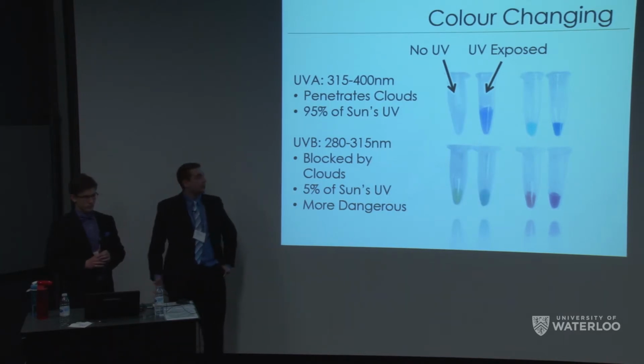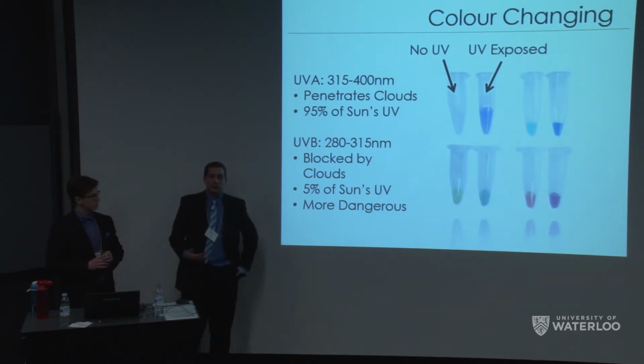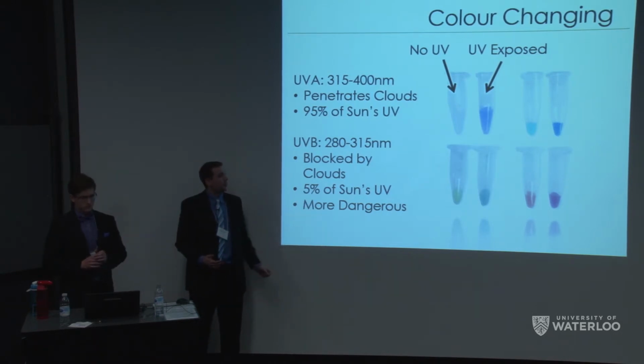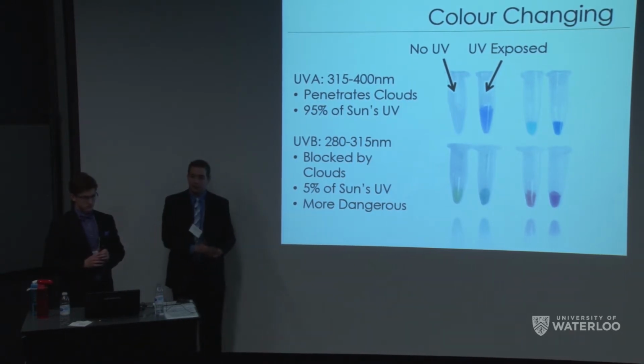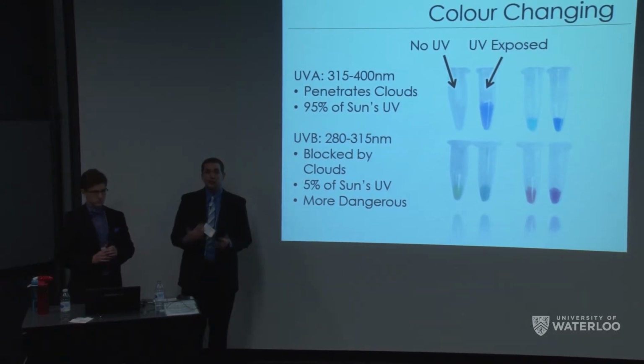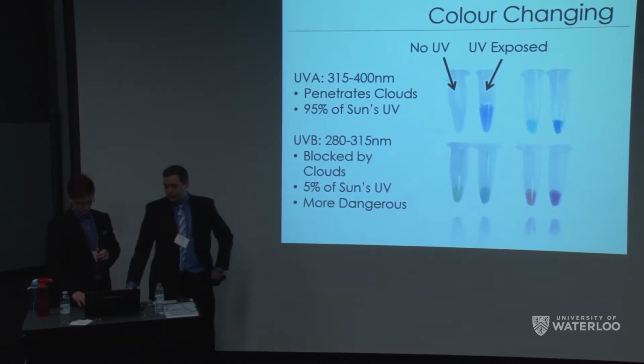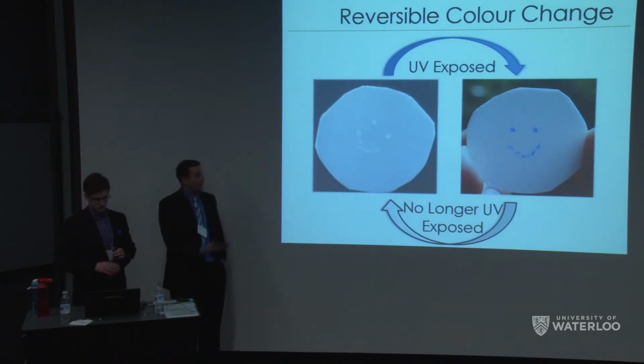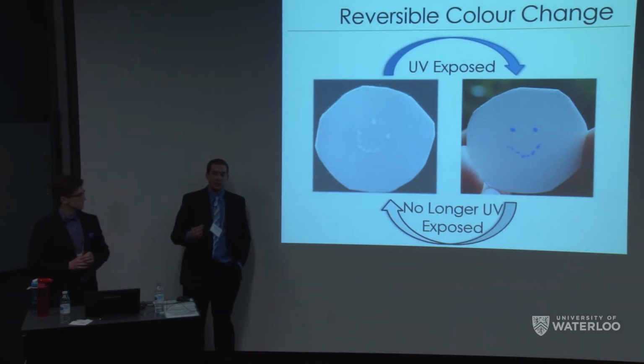What we've been able to show is that in the presence of both of these, we've induced a color change in our ink solution. You can see there are 4 examples here of different color changes we've been able to achieve just by exposing to UV light and then reversing that by exposing it to regular light, which is again what we see here.